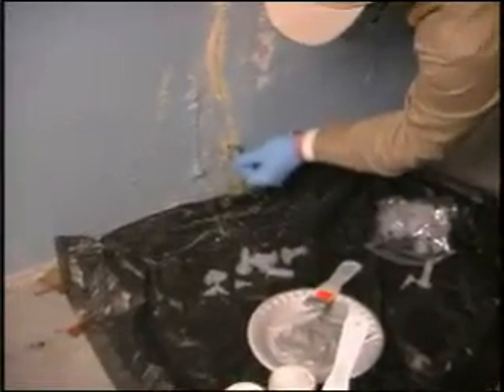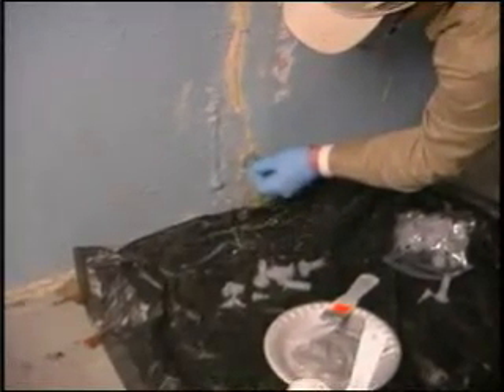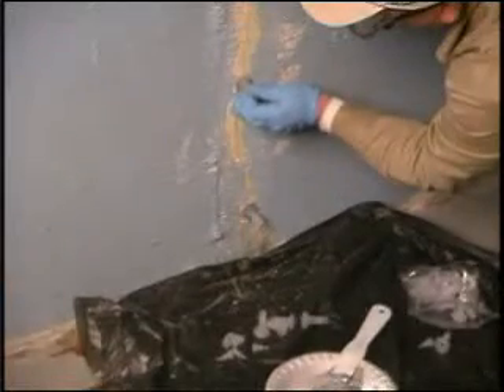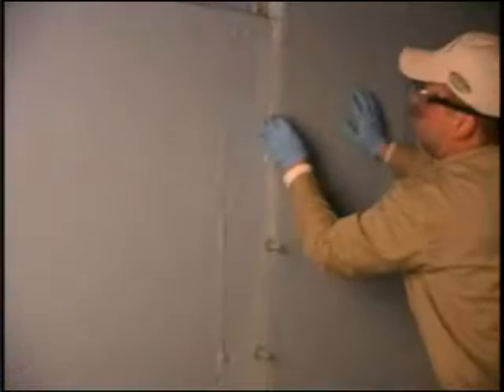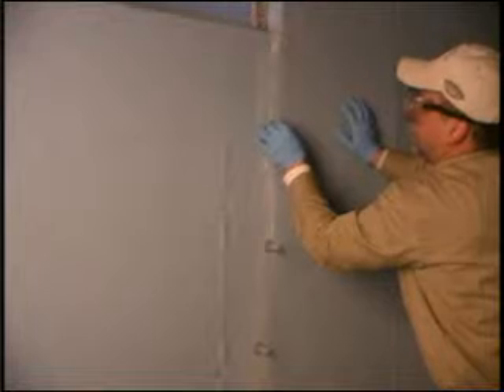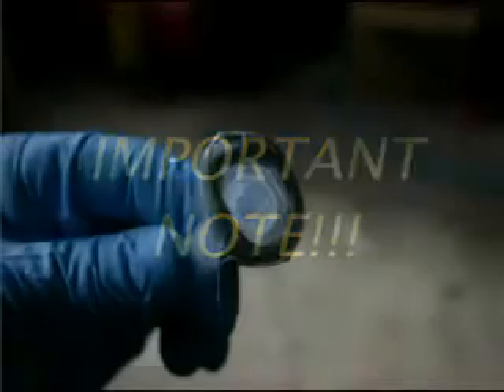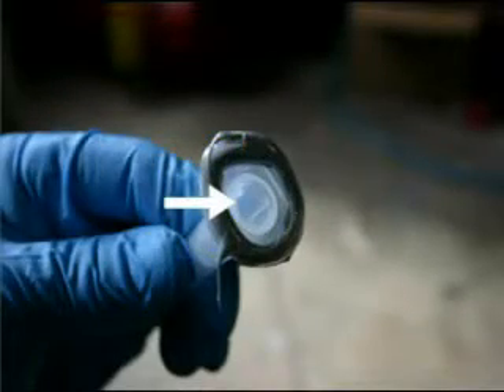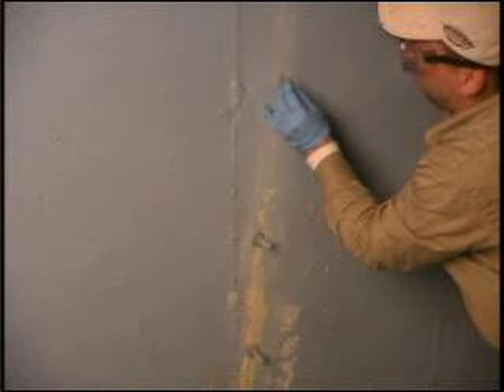Place the first port starting at the bottom of the crack and repeat every 8 inches until the entire crack is ported. Note: do not allow epoxy to block the bottom of the port opening or the crack under it.